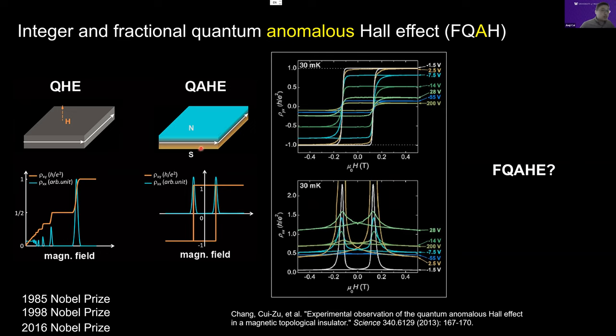And people used MBE-grown chromium-doped bismuth selenide and observed the so-called quantized anomalous Hall effect, which is the zero magnetic field version of the quantized Hall effect. So what we can see is that if you put this MBE-grown sample at very, very low temperature, you can observe two phenomena. One is that you see a hysteresis loop when you sweep the magnetic field up and down. That's the hallmark of ferromagnetism. And the second thing is that your longitudinal resistance goes to zero at zero field, and your Hall resistivity is quantized in units of h over e squared. Okay, that led to the discovery of the so-called quantum anomalous Hall effect.